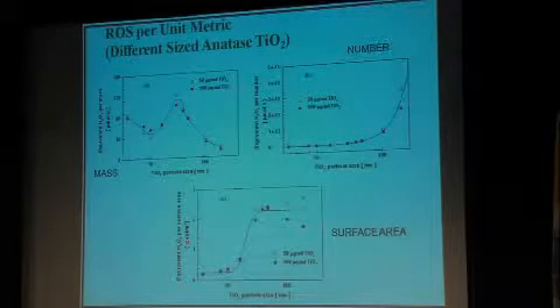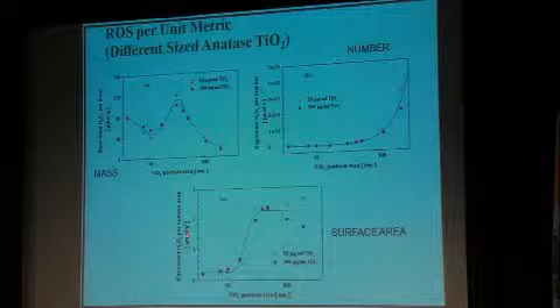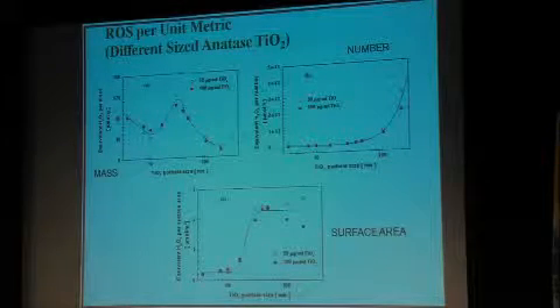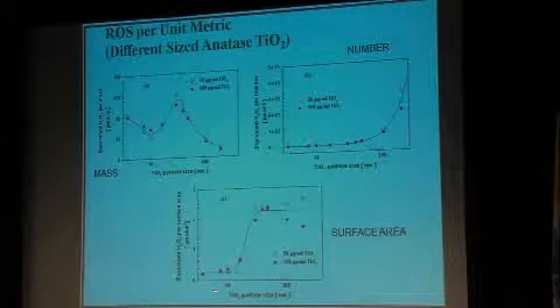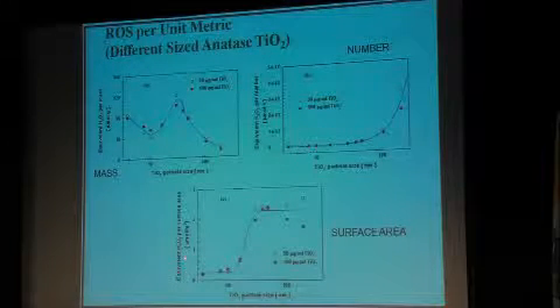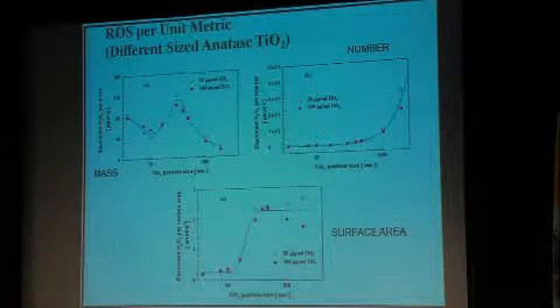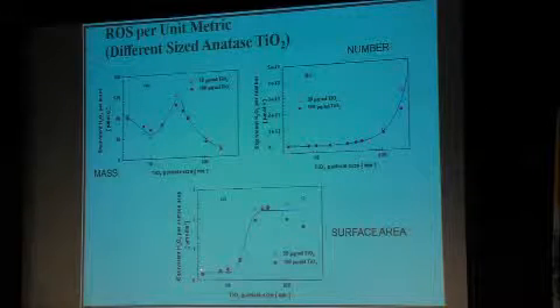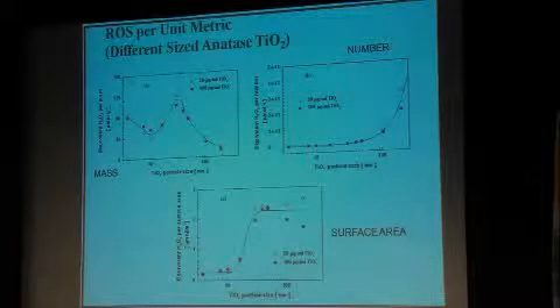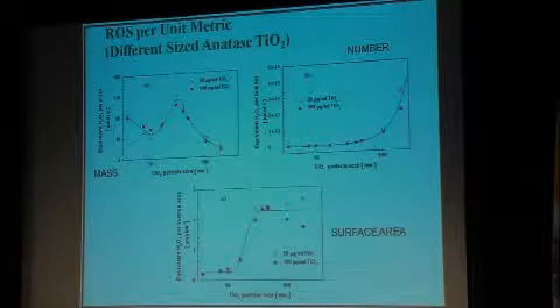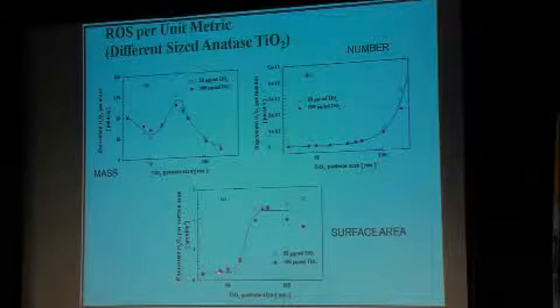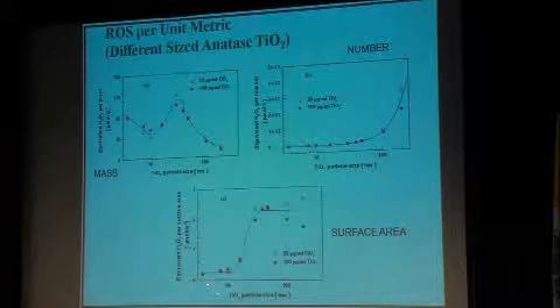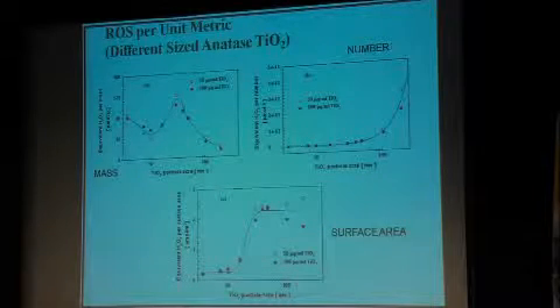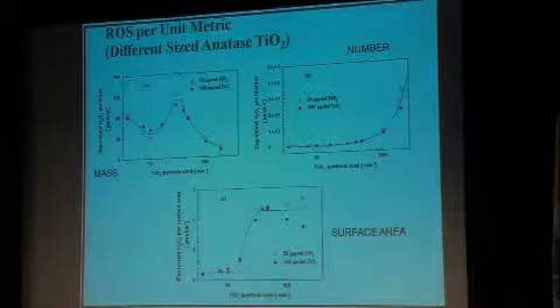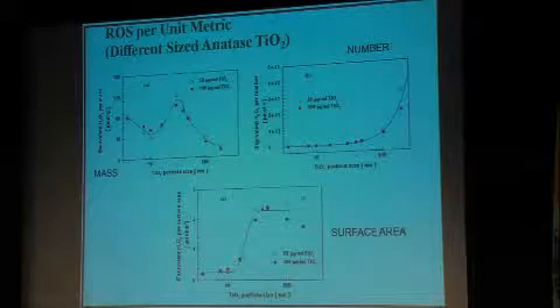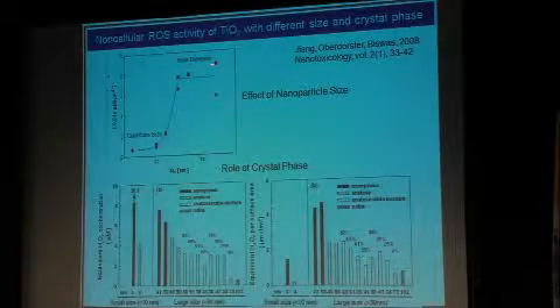And now I normalize the ROS production per unit surface area, and maybe there seems to be a trend. And you can see now these small particles have a lower potential to produce ROS. Now very contrary to what people think, but this has been normalized by the surface area. The available surface area is so large that the active sites are actually lower per unit surface area. So we feel that this is a more representative measurement, and things like that need to be done before we can interpret effects of size and so forth. And again, this is repeated.